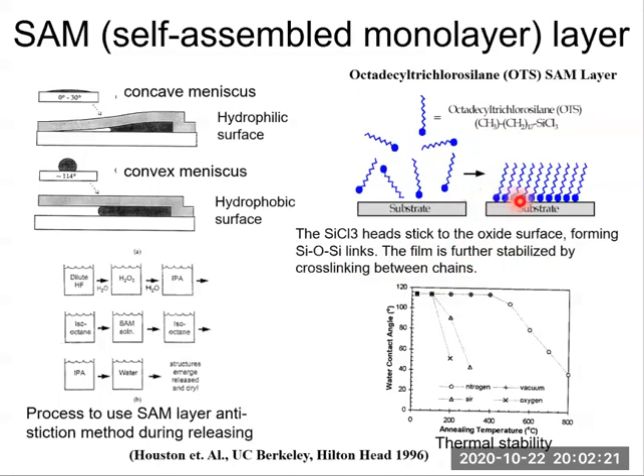So now, after coating this OTS assembly, the silicon surface is covered by a well-packed OTS assembly. And the alkyl chains stick out and convert the hydrophilic silicon surface, due to native oxide, to a hydrophobic surface. So now the surface becomes hydrophobic, which can avoid stiction. So that's the operating principle of OTS assembly.